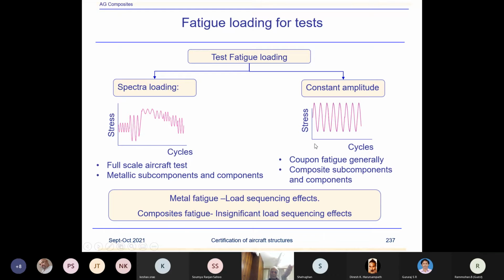And constant amplitude, where you consider that the whole of the flight is represented by constant amplitude cycling, and you test it. For a full scale test, generally, suppose you have a metallic part. Now metal is highly sensitive to the fatigue spectrum loading, low-high, high-low cycles. When you want to test a component or subcomponent made of metal, you have to apply the right type of spectral loading in order to capture the effect of the load sequencing. It's very important.